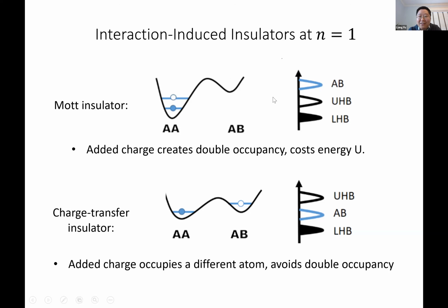Okay, so in this description, the AB sites, the cation sites, can be completely neglected. So we're just dealing with basically a single band Hubbard model, and this is Mott physics. On the other hand, if the energy difference between cation and anion is small compared to the on-site Hubbard U, then doped charge prefers to go to the cation sites. So the added charge now occupies a different type of atom, and in this way, it avoids double occupancy. So this is the so-called charge transfer insulator.